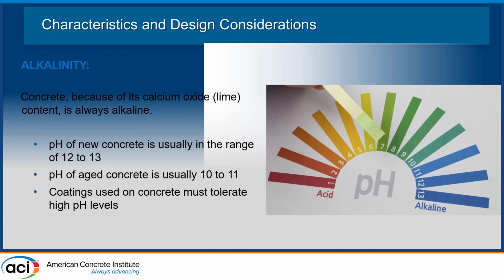So we recommend a pH test after the surface prep is done to ensure that we've got fresh, high pH concrete. If after the surface prep there's still a low pH, we need to do more surface prep. We remove more of that contaminated concrete until we get to a good pH that will contribute to a good coating system.